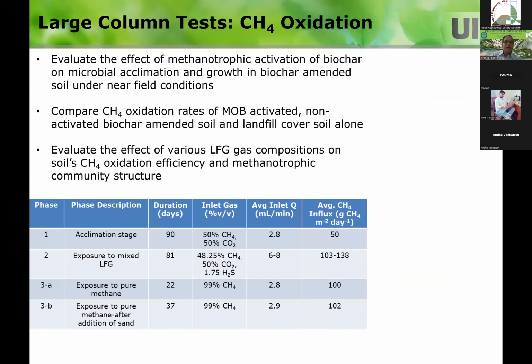And then we got the results. We basically ran in different phases: phase 1, phase 2, phase 3A, phase 3B. The first stage is the acclimation stage. In the second stage, we expose it to the mixed landfill gas, and then we can simulate whatever we want. In 3A, we just put in methane alone. And in 3B, we exposed pure methane after addition of the sand on the top. So we tried to design different phases of the testing to understand what is happening under different gas conditions.